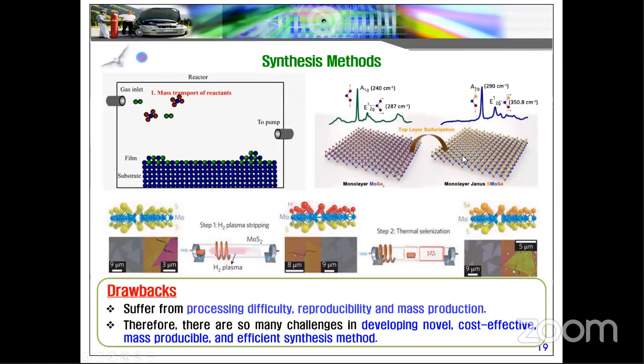In the conventional methods for transition metal chalcogenides, we need to grow the transition metal chalcogenide, especially molybdenum or any other chalcogenide. We can get a single layer, not bulk, because we need to develop something simple and scalable. Scalability is questionable for the CVD methods. That is the problem. Another thing is that CVD methods need high temperatures, and we need to use many different types of carbon sources, especially acetylene and methane gases. Acetylene and methane gas also pollute the environment. In order to avoid these issues, we need to fabricate the transition metal chalcogenides with a simple fabrication technology, and that method should be scalable and low cost.